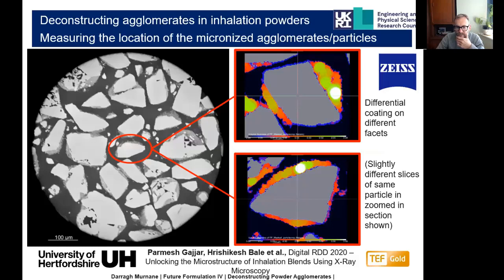When we image these blends in 3D, we can start to pick out individual lactose crystals. They're those large particles, but we can also start to see these diffuse regions around the particle coating. So because of the density difference of these porous areas, we're able to pick out what is the drug coating phase around the coarse lactose particles.